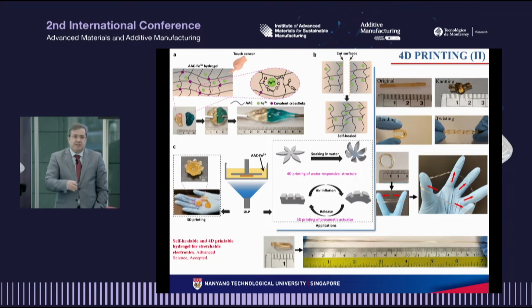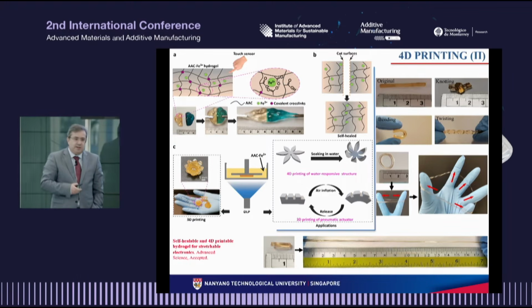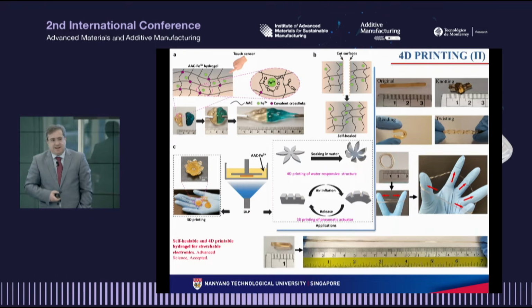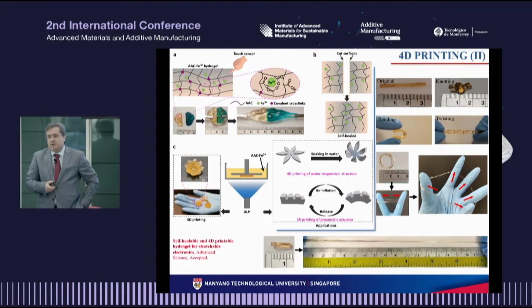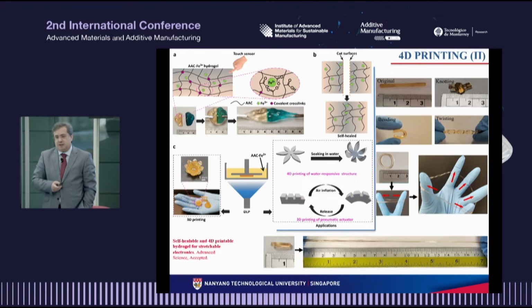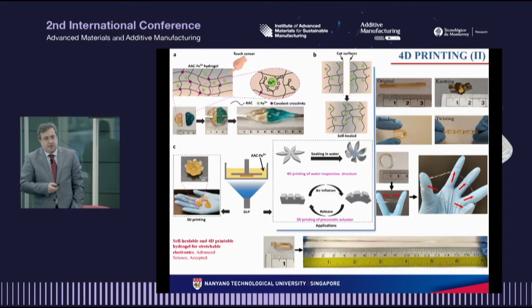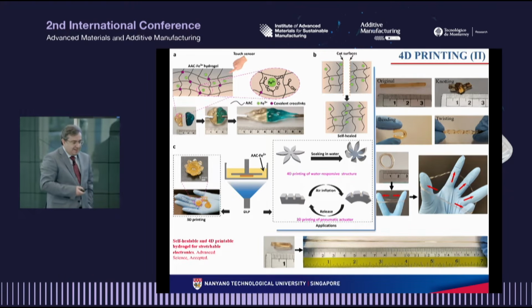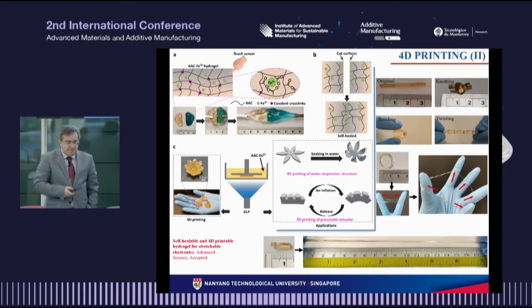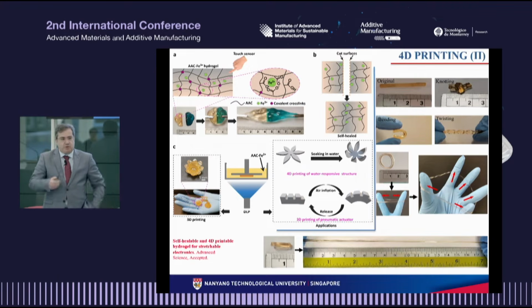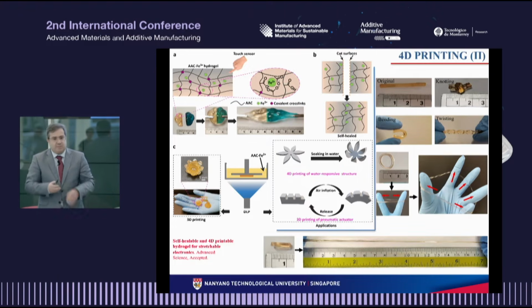And the challenge is the difficulty to create a single component showing high electrical properties, self-healing, shape morphing, and stretch stability. We solved this problem by designing a hydrogel, a dual cross-linkable hydrogel, comprising covalently cross-linkable acrylic acid and iron ions through the formation of a reversible ionic network.